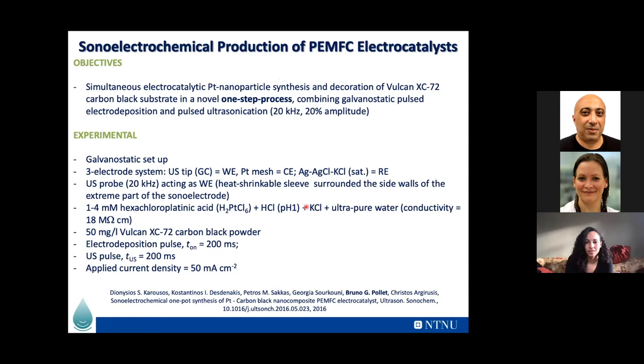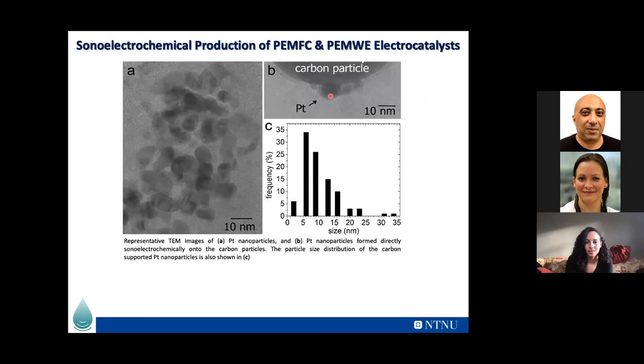Carbon substrate. And we also did some electrodeposition pulse at different time regimes, if you like. So we've got some interesting data here. This is a nanoparticle of platinum on the carbon particle here, and we got an attractive particle size around 5 nanometers in distribution. This is a TEM image. You can see those nice platinum nanoparticles on the carbon substrate.